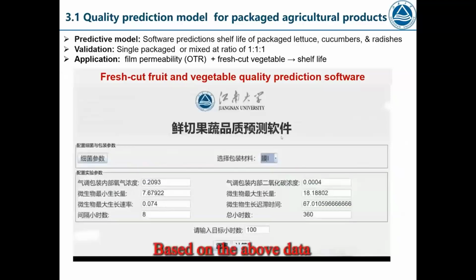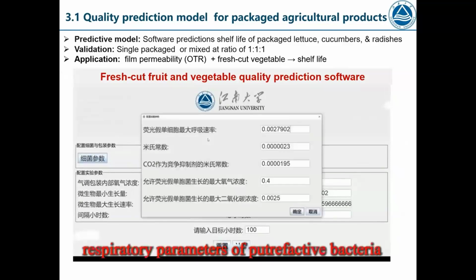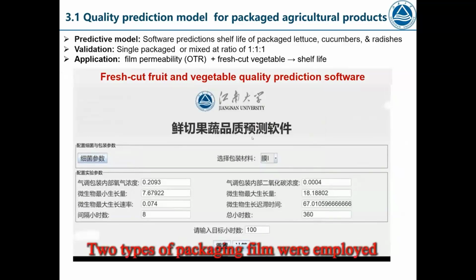Then we designed a model with the prediction equation. The software could predict the shelf life of each kind of packaged vegetable and also their mixture. It means that we could set 2 of 3 key factors, including the kind or OTR value of film, a certain fresh cut vegetable, or a certain shelf life. Then the remaining factor could be predicted.